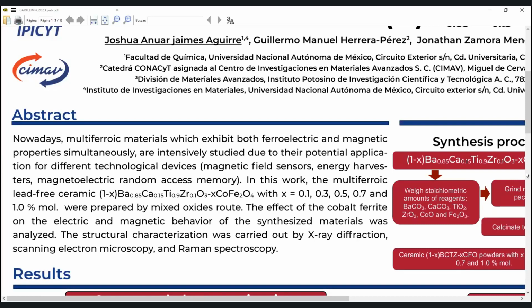In this work, the multiferroic ceramics BCTZ-CFO with x equal to 0.1, 0.3, 0.5, 0.7, and 1 molar percent were synthesized by the mixed oxide method. The effect of cobalt ferrite on the electrical and magnetic behavior of the ceramics was studied. X-ray diffraction, scanning electron microscopy, and Raman spectroscopy analysis were also performed in order to characterize the structure and morphology